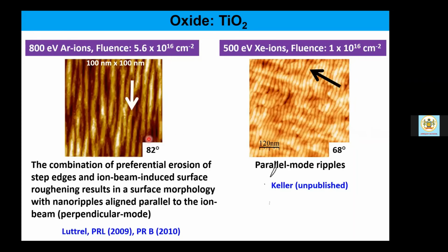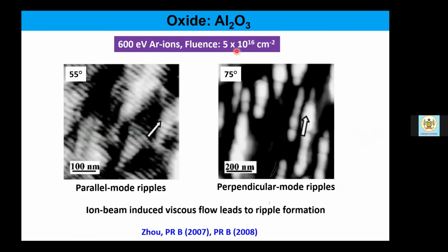I mean, these perpendicular mode ripples, where the ripple orientation is parallel to the incident ion beam direction, happen only at higher incidence angles. This is the case of Al2O3. Again, parallel mode ripples are formed at 55 degrees itself, and perpendicular mode ripples are seen at very high angles, as expected. Here, ion beam induced viscous flow also plays an important role, which has been reported.